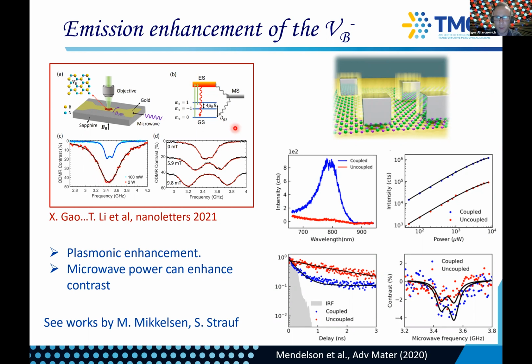So 50%, it's about 3 times as large as your NV center in the best case scenario. Yeah, and with the magnetic field, it splits as expected. So it's really, not only can you basically engineer these defects in atomically thin materials, but you can then also have a very strong ODMR contrast. So this work is really remarkable because you don't need to collect data for a long time. This contrast is really quite huge.